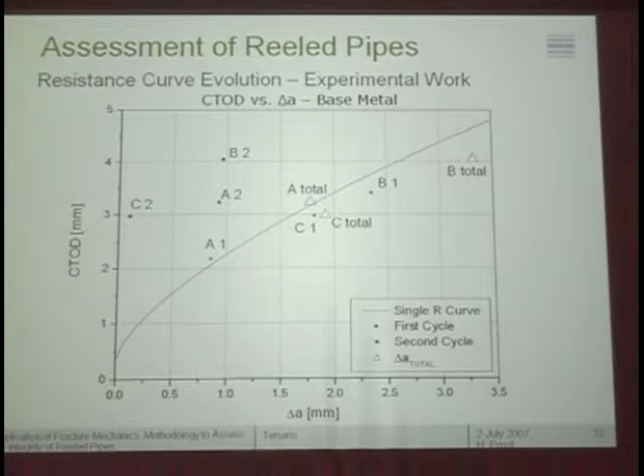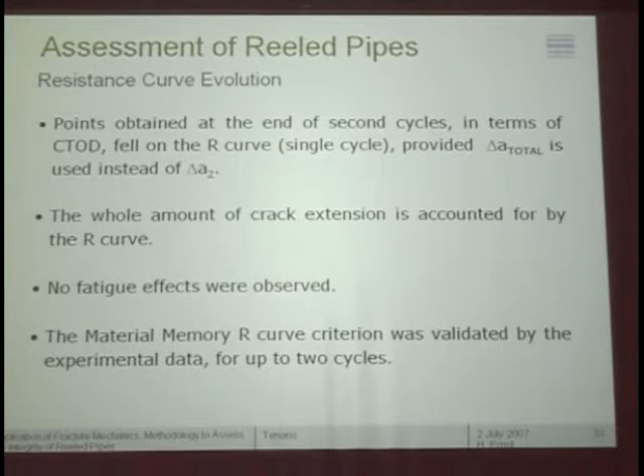The same thing goes for the other material. It's a little busy, but basically it's the same. When I put everything in terms of the total crack extension, in the three cases, you get pretty much an agreement with the points and the curve. So, in short, regarding the resistance curve evolution, points obtained at the end of the second cycle in terms of the CTOD fell on the resistance curve, provided the total delta A is used instead of delta A2. The whole amount of crack extension is accounted for by the resistance curve.